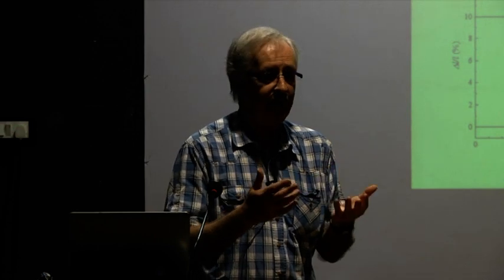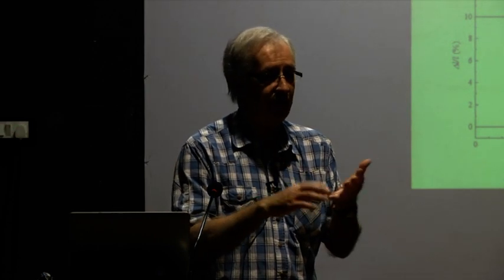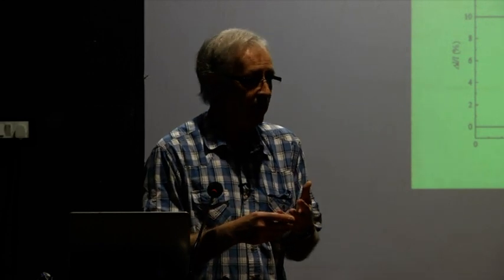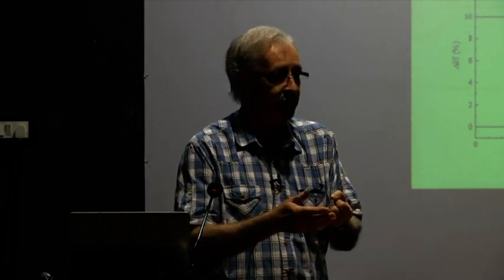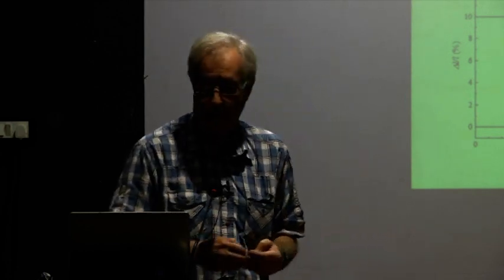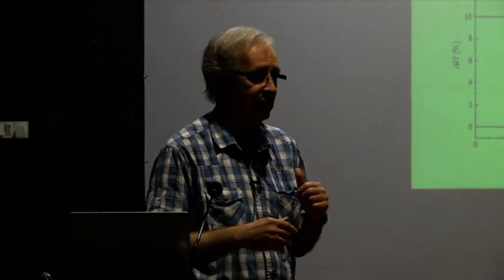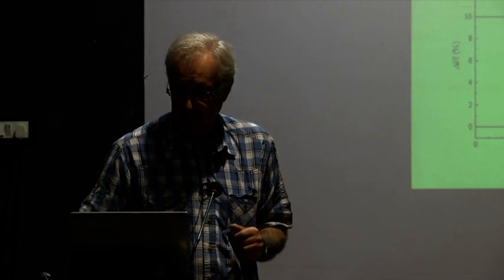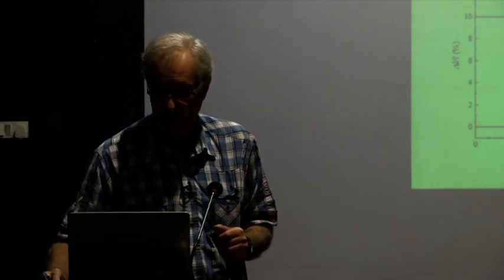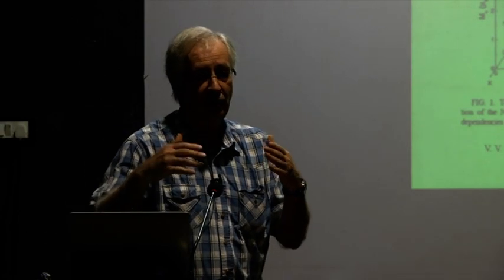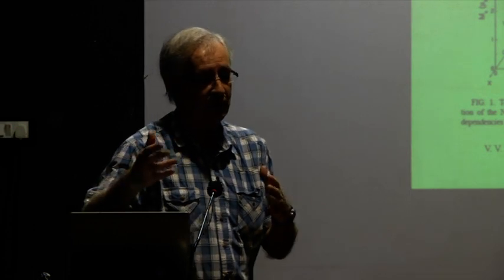You have your Zeeman energy. It's the magnetization times the magnetic field, which is not very much as an input energy. So you're not going to get more out than what you put in. So the amount of work that you're going to get out of these materials is not that much at the moment. So when we go to the magnetization, this will become more obvious when I show you the magnetization of the other materials.